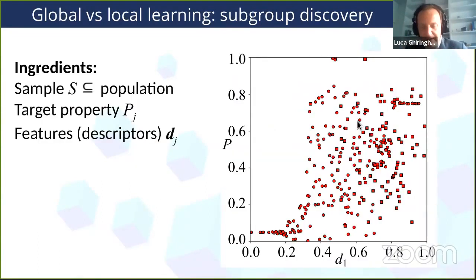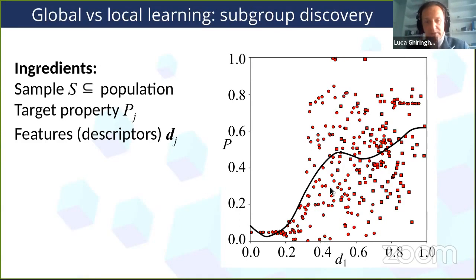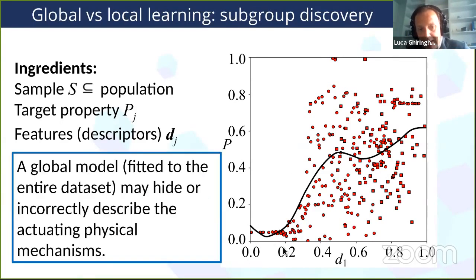Let's go to a slightly more elaborate example, and let's say that we have so many data points. So we have a population, and we have some target property P, and we have some features here. So this is only one. And you try to make some kind of a good fit of this data. And this is the best maybe one can do with this cloud of points. And you say, well, maybe I'm not satisfied. You may notice that if you focus in this area of the descriptor, you have a much better fit, especially if you do a horizontal line here. So if the value of the descriptor is smaller than 0.2, you would have a much better prediction for these data points than for the whole model.